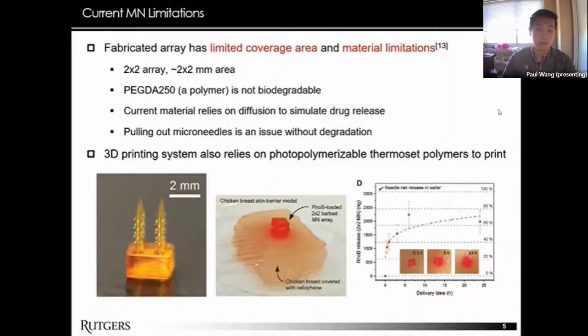Additionally, pulling out the array is an issue because the barbs are still present. As I mentioned before, our microneedle has 18 times the adhesion strength of a barbless microneedle, which means it's 18 times harder to remove. Because of that, we need our needles to dissolve or degrade while inside the skin, so that once the drug release is complete, we can remove it easily. Our 3D printing system also has its own requirements. The system requires photopolymerizable thermoset polymer solutions as a material to print microneedle arrays, which prevents the use of biocompatible, biodegradable, bioresorbable materials. So until these issues are addressed, our microneedles are not really useful for practical applications.